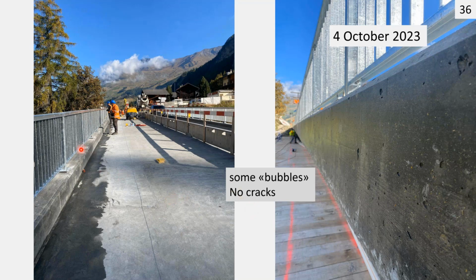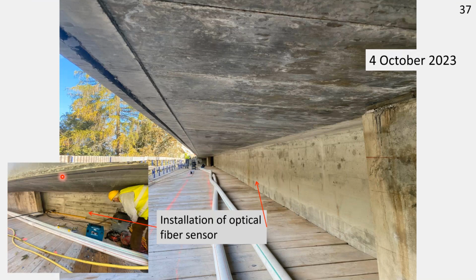Because when you cast a curb in reinforced concrete to an existing slab or a slab that is older, then you have transverse cracking. You cannot avoid that. But in our case, we have higher requirements. We do not want to have cracks in the curbs.